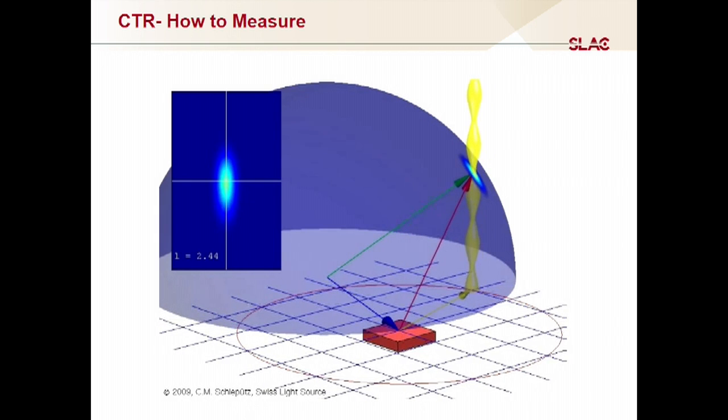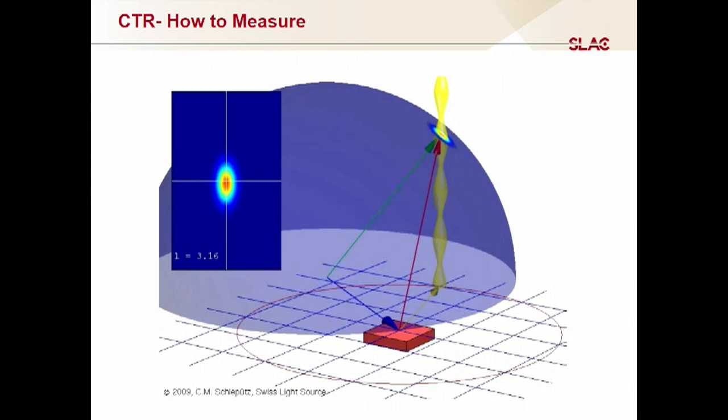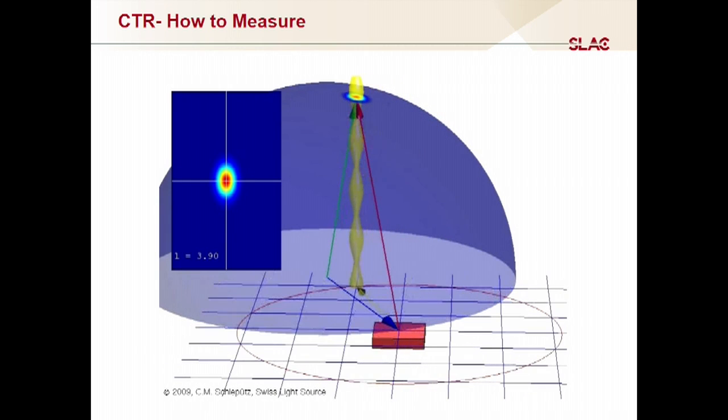And so there it's getting weaker. You're going to come up close to a Bragg point. It also shows you L here, so as L gets close to an integer value, this will get stronger. So as it approaches 4, it starts to get strong again. When it's at half integer values, it's at its weakest. So when you're away from the Bragg points, it's very weak. When you're close to the Bragg points, it's very strong.